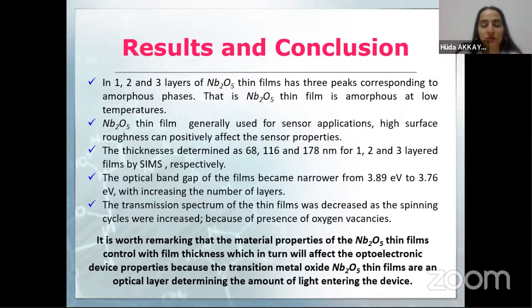Then the transmission spectrum of the films decreased as the spinning cycles increased because of the presence of oxygen vacancies. And to summarize briefly, it was remarked that the material properties of the niobium pentoxide thin films are controlled by film thickness, which in turn will affect the optoelectronic device properties. And because the transition metal oxide niobium pentoxide thin film is an optical layer determining the amount of light entering the device.